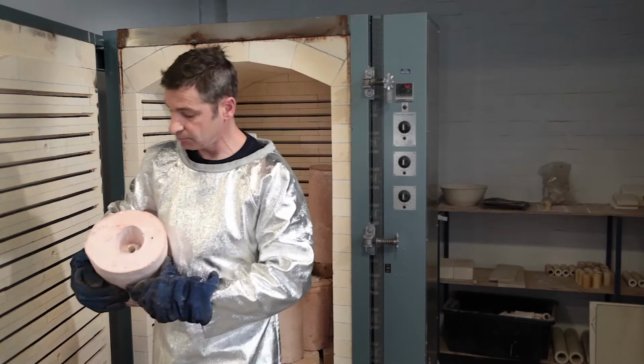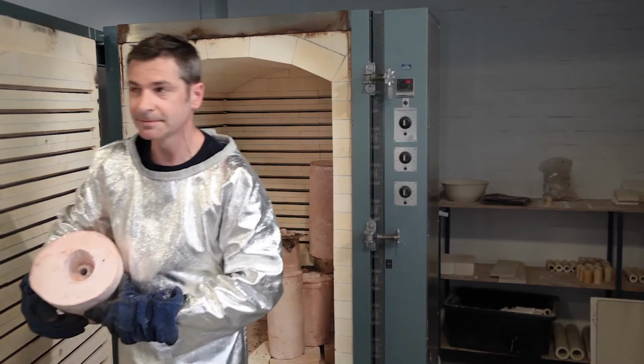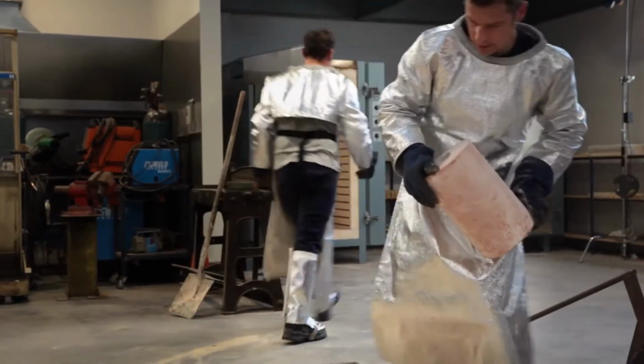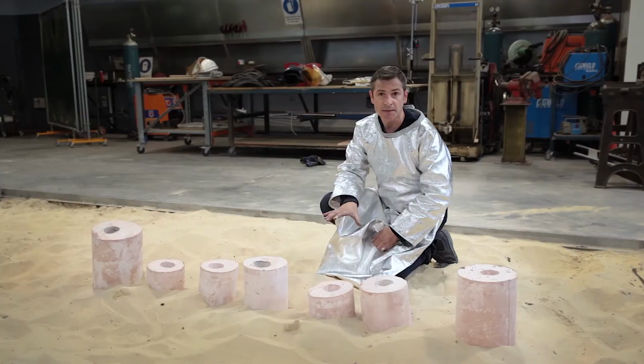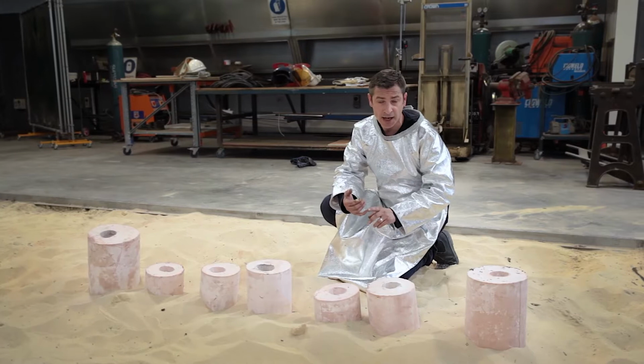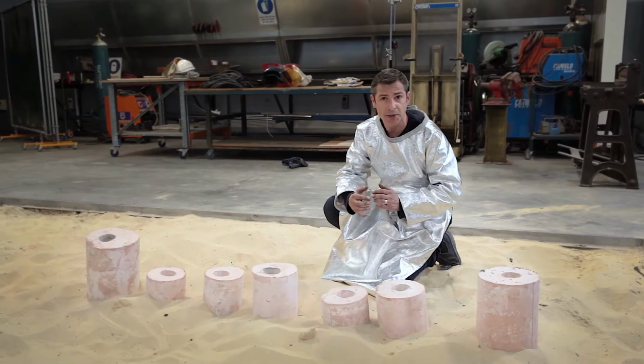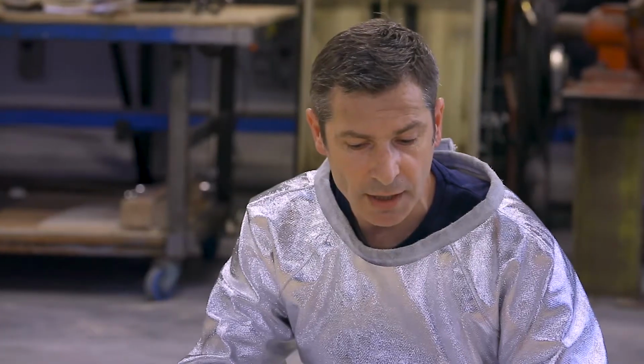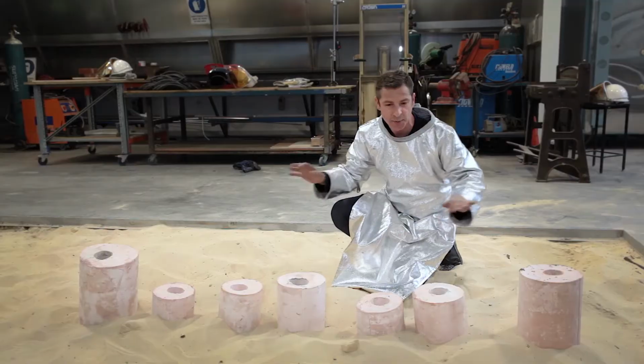650 degrees, clean as a whistle. We've just taken the moulds out of the kiln. They're at 200 degrees. We put them in the sandpit to maintain the temperature so there's no shock when the metal goes in. Also, in case there's a spill, a mould may crack, the metal can pour everywhere. So it's basically just to contain it.